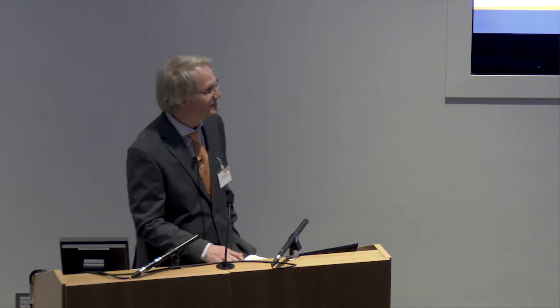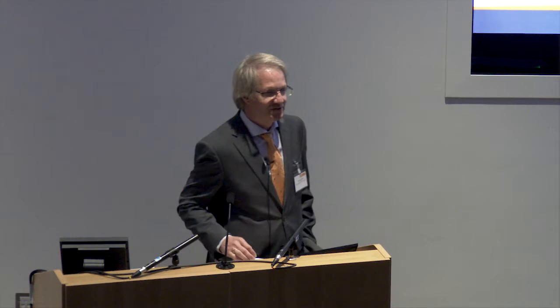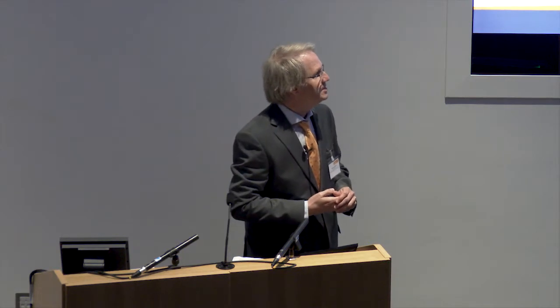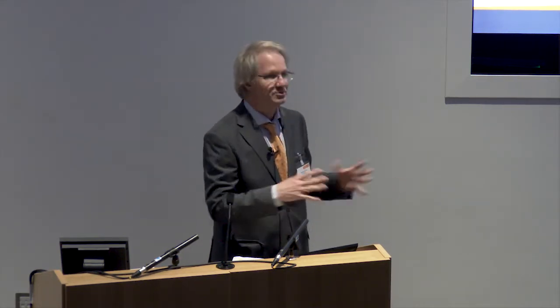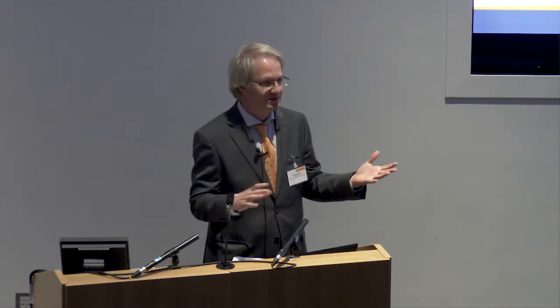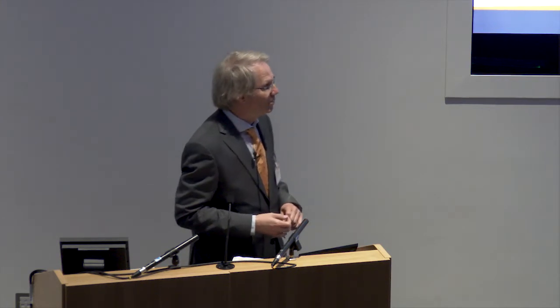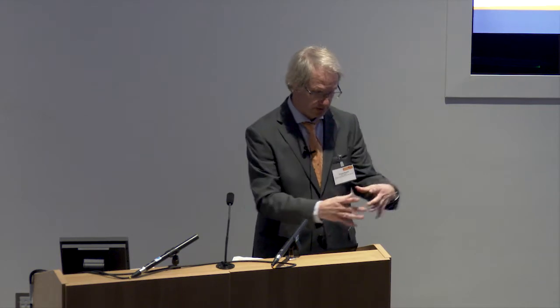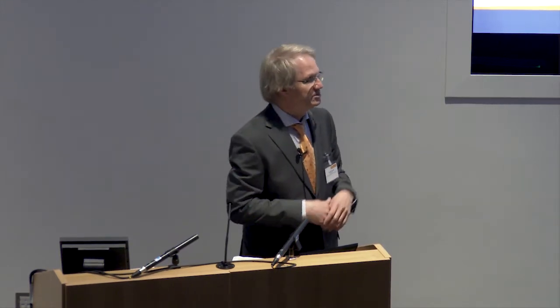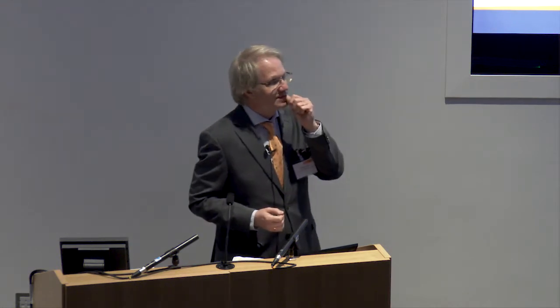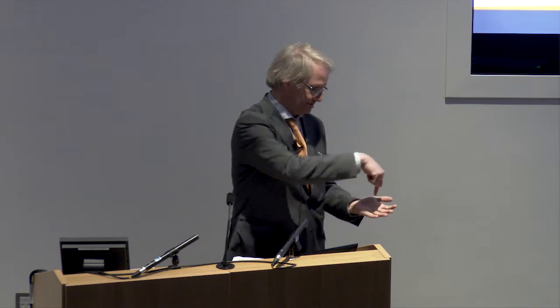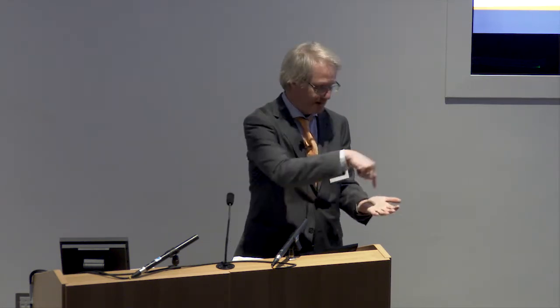The result is quite nice, but the way to it was quite long and hard. Because polishing a flat surface, you can imagine if the laser hits the part in a perpendicular way, you have a circular area of activities. But if you have curved parts, this circle will be deformed, it will become an ellipsis or whatever, depending on the curvature. So if you always use the same set of parameters and your area where something happens on the part gets bigger and smaller and bigger and smaller, you will not be able to have a stable or reliable result. And so it was investigated how the laser power has to be adjusted to the angle of incidence.